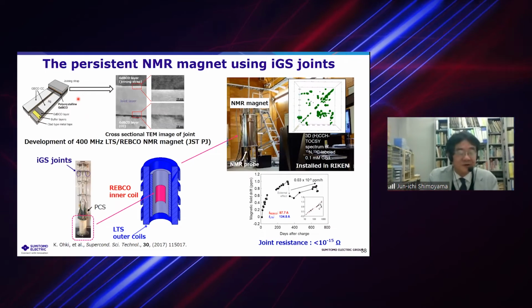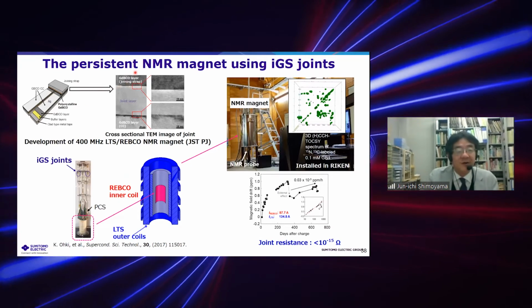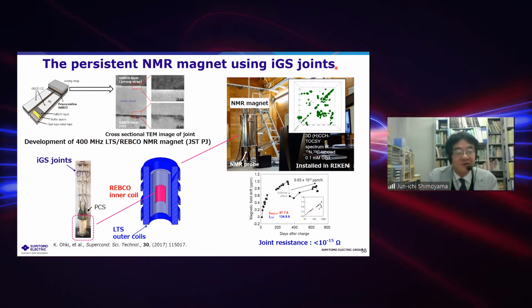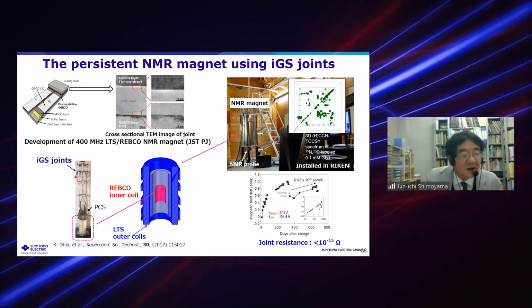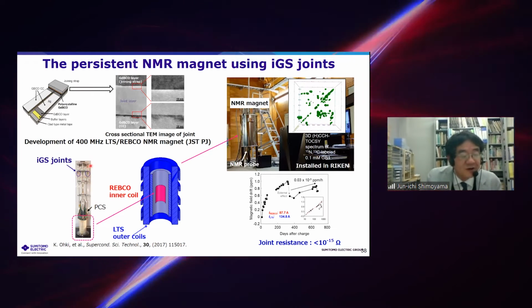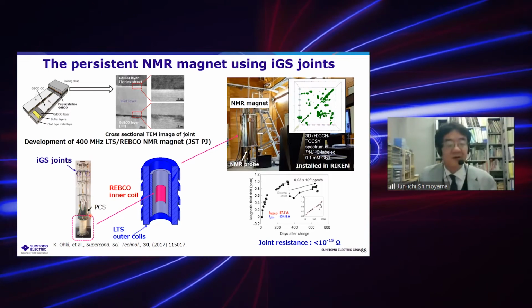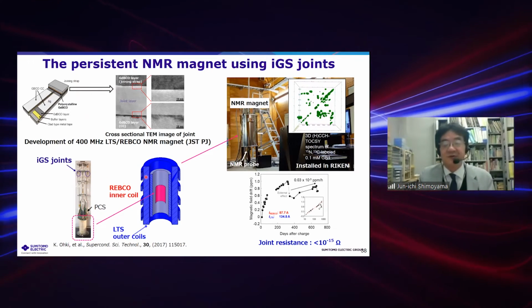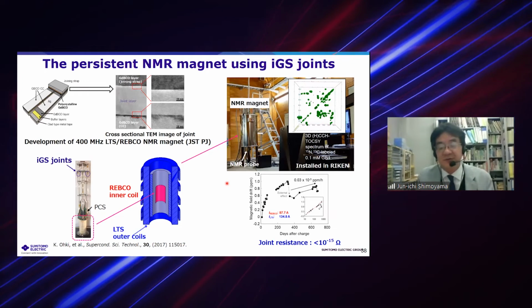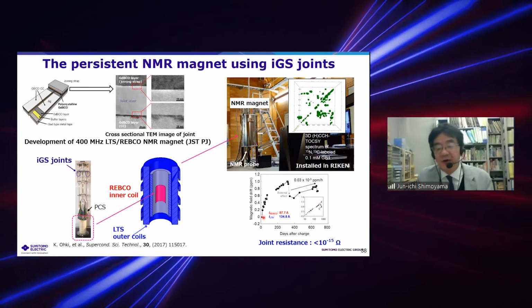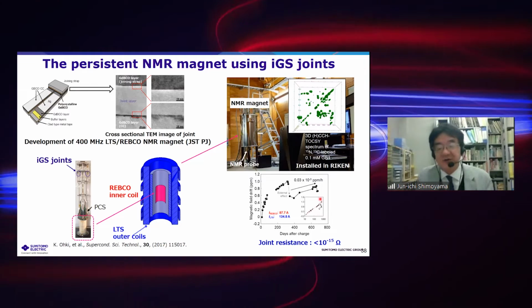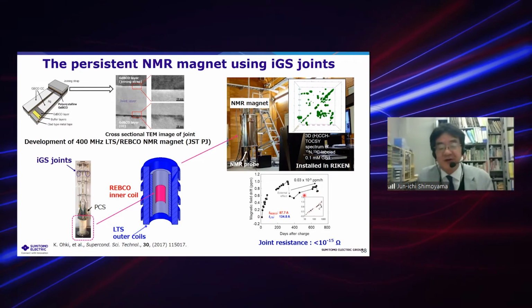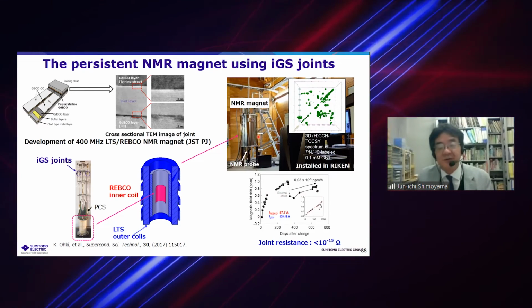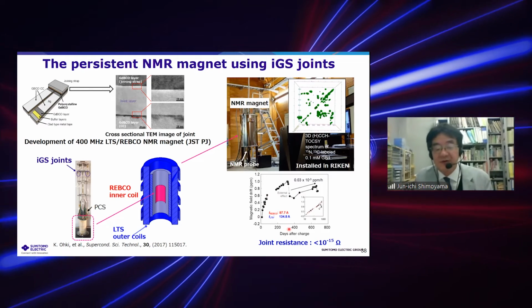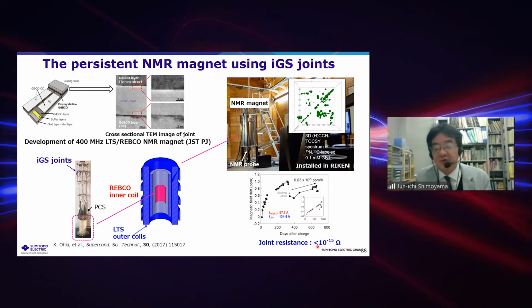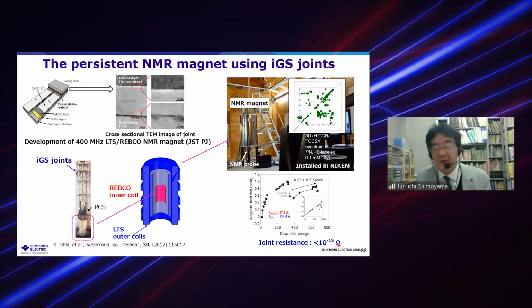Such very nice performance was also confirmed in the persistent NMR magnet using the iGS joint. So this is the iGS joint. There are 2 joints in this closed circuit, and this closed circuit was installed in the 400 megahertz NMR system and operated for longer than 700 days, as you see here. Very small change in the magnetic field in the NMR magnet was confirmed. This means the joint resistance is much lower than 10 to minus 15 ohms for a long time.